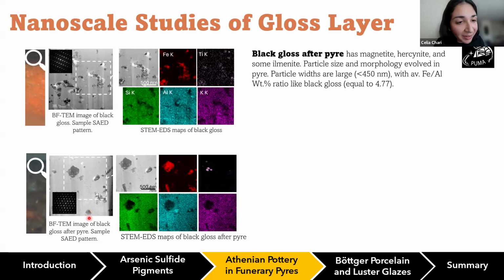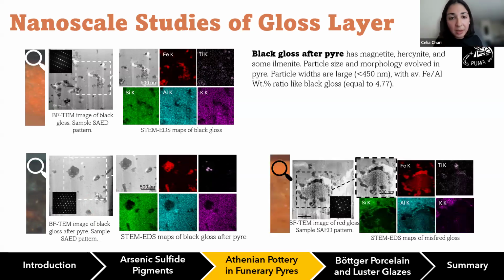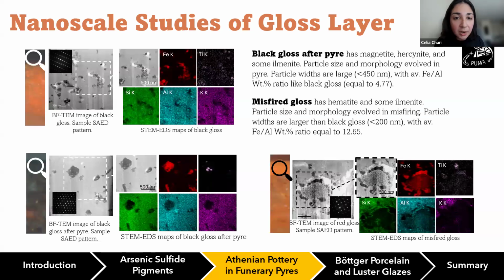They're just so small, within a micron by a micron visibility, that it's not something that is visible on a macro scale. It's kind of insignificant when it comes to the actual quality of the gloss layer. But nevertheless, there are some differences on a much smaller scale. With the red gloss, we're also seeing that there are larger particles that are forming because of the misfiring. So this is also a sign that the misfiring was due to prolonged firing times that allowed those particles to